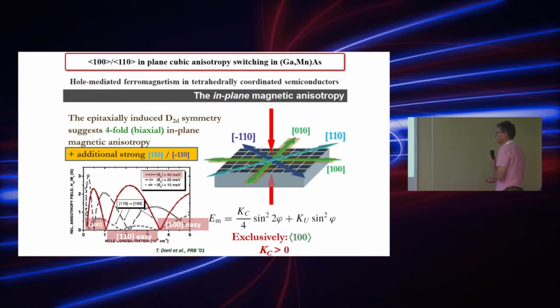However, perhaps the main obstacle to observing this rich behavior is the presence of additional strong uniaxial in-plane magnetic anisotropy between the [110] and [-110] directions in this system. So the total magnetostatic expression for this material looks like this, and in order to find switching of the cubic anisotropy constant, a relevant experiment has to be performed.